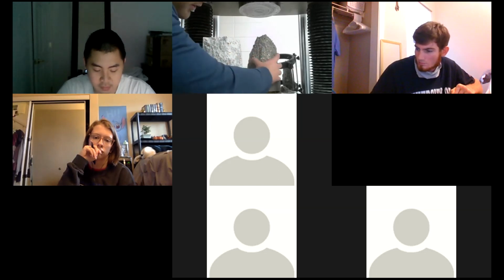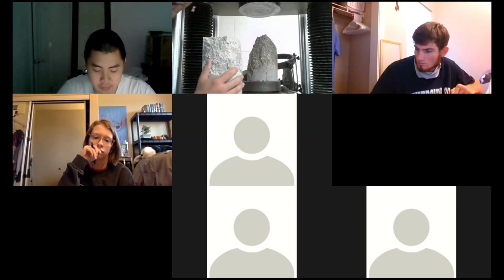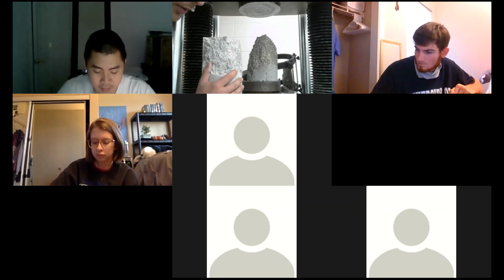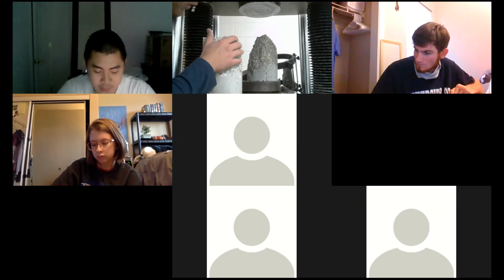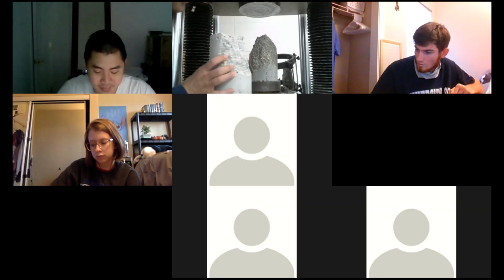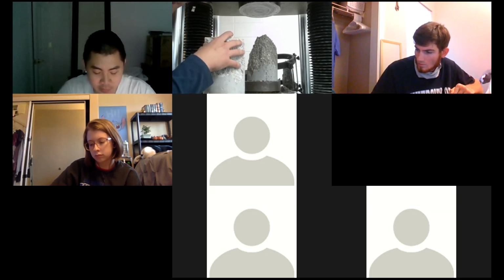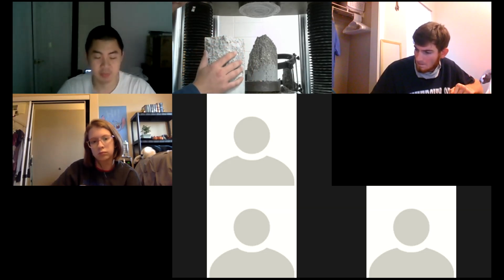But if you look at the difference, this is still wet and this is fully cured, 99% cured. So if you increase the curing time and if you provide perfect curing conditions, you get better results. And I believe the failure was only on this side. The only reason failure was on this side rather than the other side, there was a stress development. That's what I'm assuming. The stress was developed on this side and the failure started from this section. That's my only assumption.